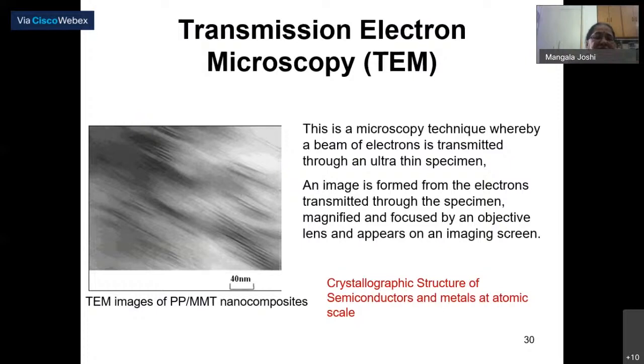This is a microscopy technique where a beam of electrons is transmitted through an ultra-thin sample. Here I would like to tell that in TEM, the most important thing is how good a sample you make. You need to make an ultra-thin sample. If you don't make an ultra-thin or a good sample, your electron beam will not pass through the sample itself. So the major challenge in getting good electron microscopy images is to have a very thin section of a filament so that the electron beam can pass through.